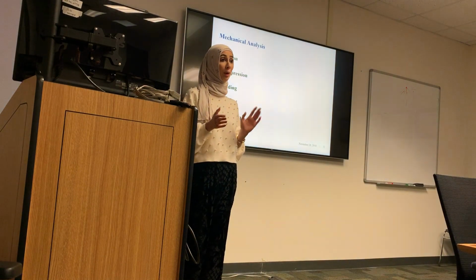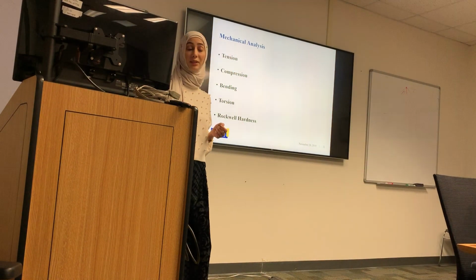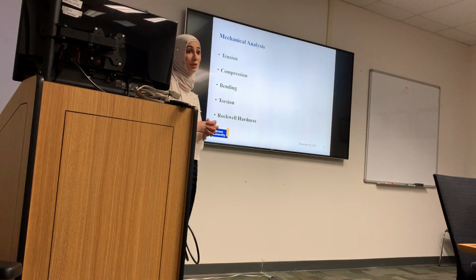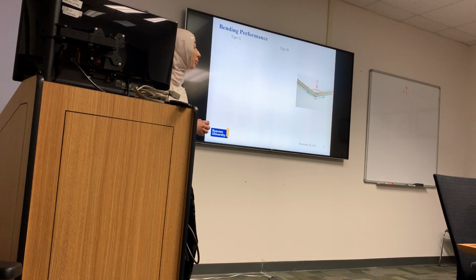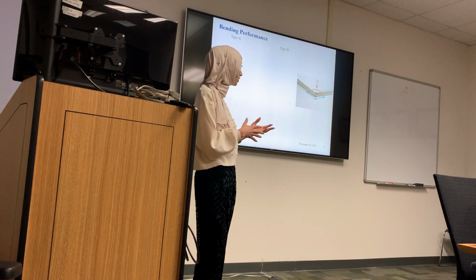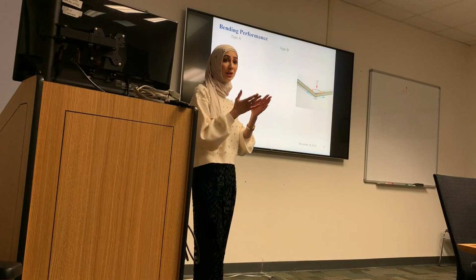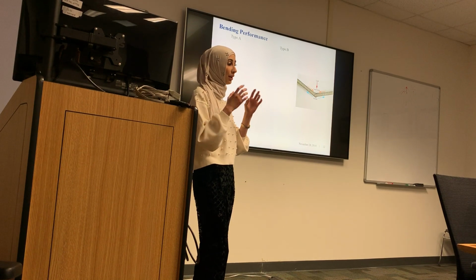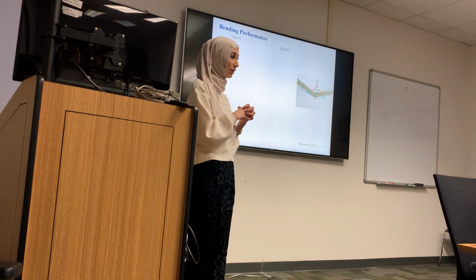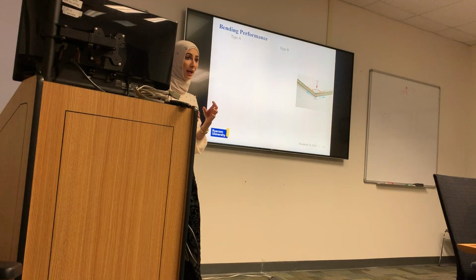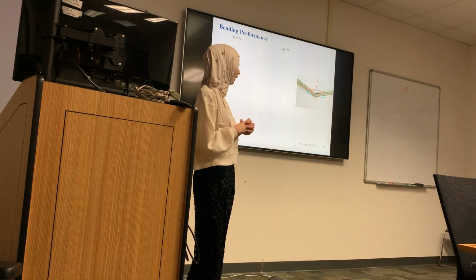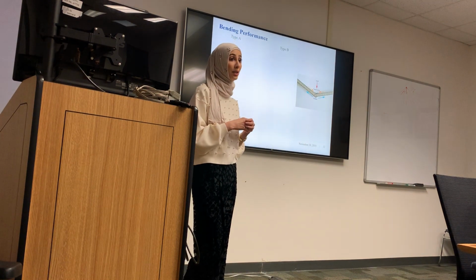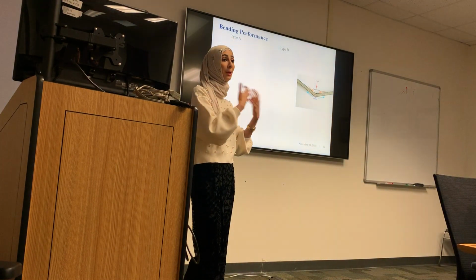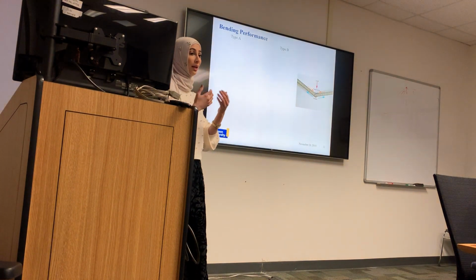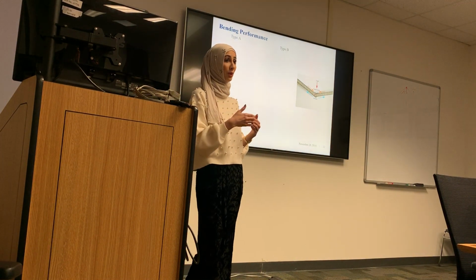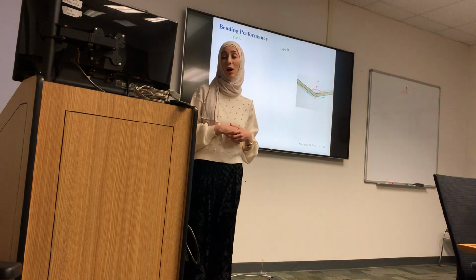Due to the limitation of time, I'm only going to cover the bending. It's one of the important characteristics related to the sandwich structure. As we know, bending is a combination of 3 loads: compression, tension, and shear. The outer layers, which are the carbon fiber, handle the tension and compression, whereas the core layers hold the shear stress. There is a theory behind having a thick, low weight core. Whenever we increase the thickness, we increase the moment of inertia, and the moment of inertia is inversely proportional to the maximum stresses on both carbon fiber layers.